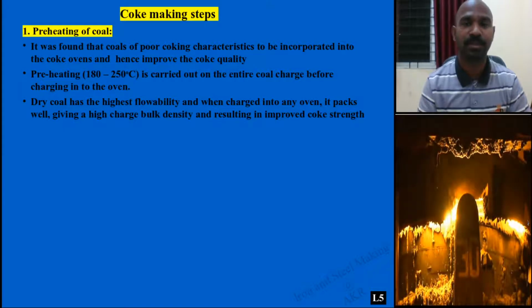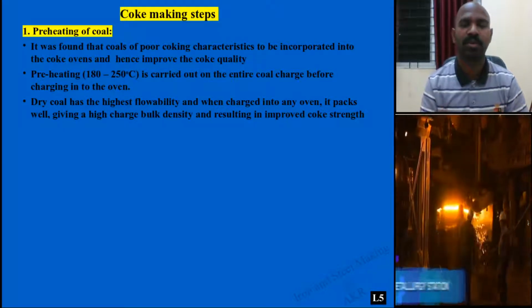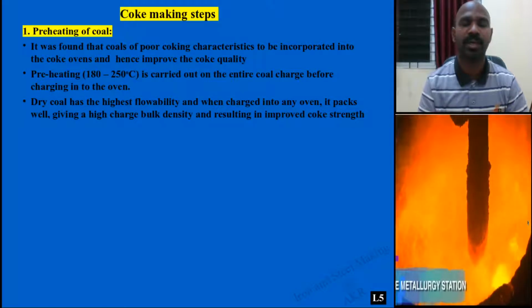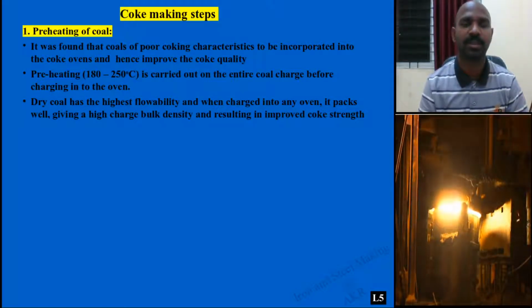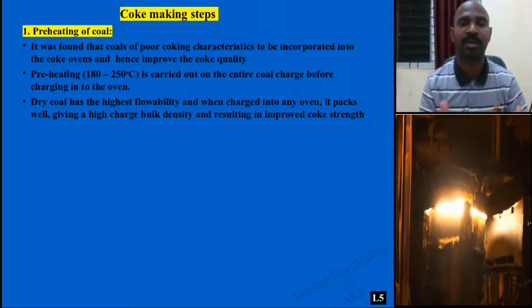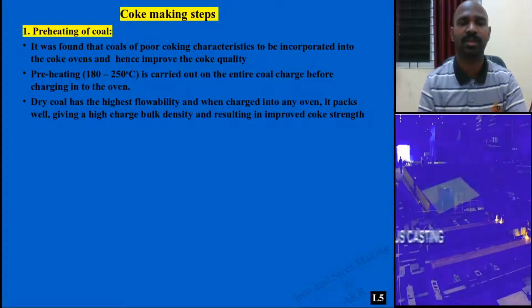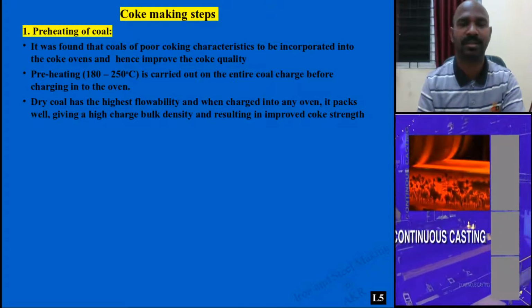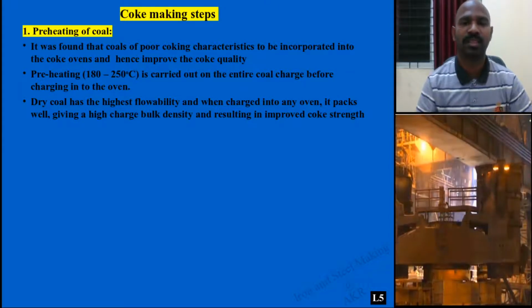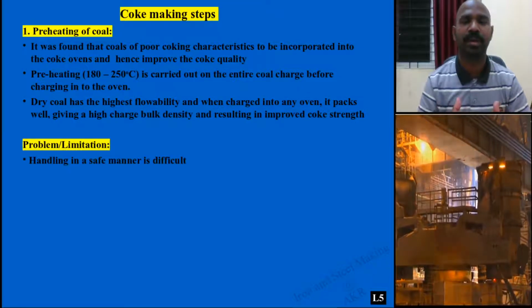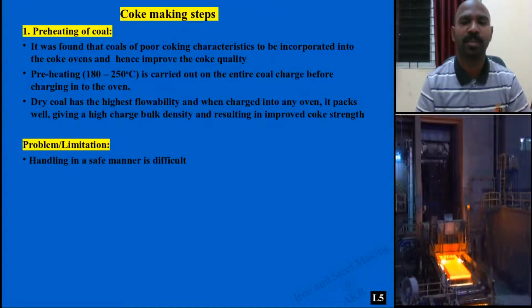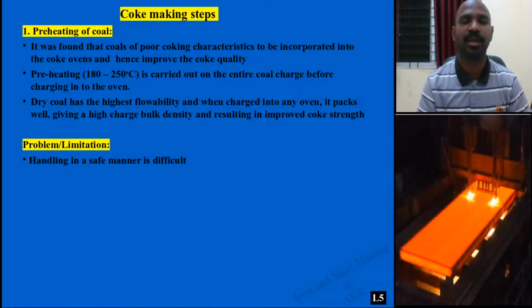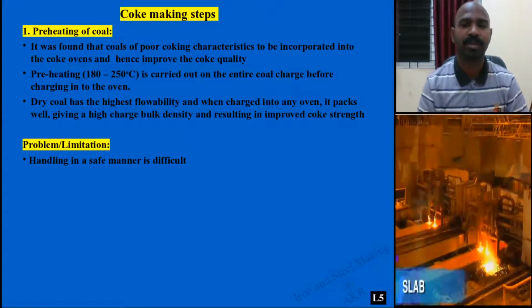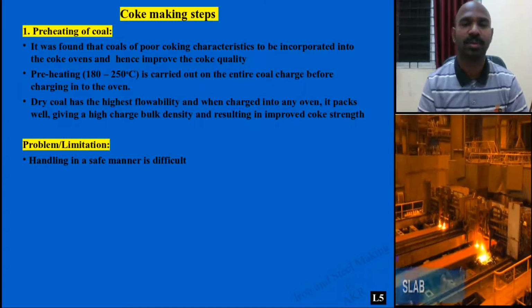Bulk density improves. As a result, bulk density, coke strength, coke reactivity, and coke strength after reactivity all get improved after coke making. So that is why the preheating of coal is essential. The problem is handling it in a safe manner. This particular step is difficult because it involves large temperatures and dust loss.